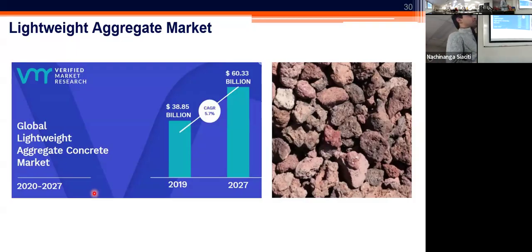So currently the lightweight aggregates are produced by extracting natural shale and clay, subjecting those shale and clay material to excessively high temperatures around 2,500 degrees Fahrenheit. So you need to use a kiln and sinterize your natural extracted type material. And that process is very expensive and with also a fairly high carbon footprint. So imagine talking with the different producers, one of the major pain points that they have is that out of the total cost of these lightweight aggregates that they produce, almost half of it goes to the cost and covering of the utility expenses for these materials. So these are fairly expensive, environmentally unfriendly type of material.